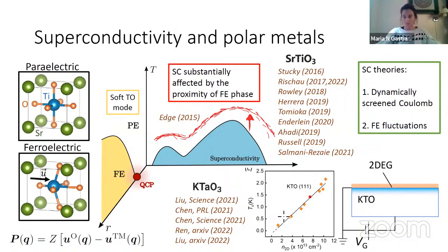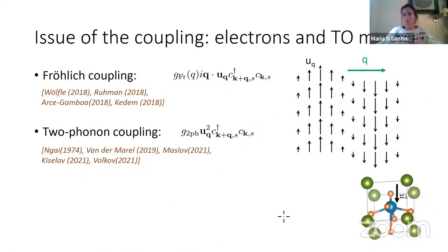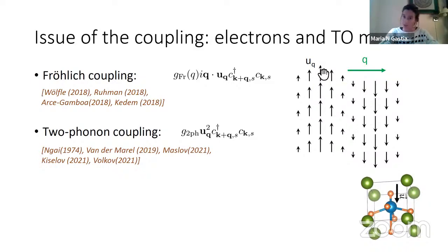So with this, I'm done with setting up the states, and I'll go into the issue of how I couple the electrons and this ferroelectric mode, which is a transverse optical mode. I'm showing it here with a little bit more detail, if you want a cartoon, where I'm showing the local displacement, this dipolar displacement U of the phonon, which is propagating to the right. That means that U and Q are perpendicular. So when you go to the linear coupling in a textbook of electron-phonon, you find the ferroelectric coupling. This one is Q dot U. That means that if your displacement is perpendicular to the propagation, in principle, this vanishes exactly.